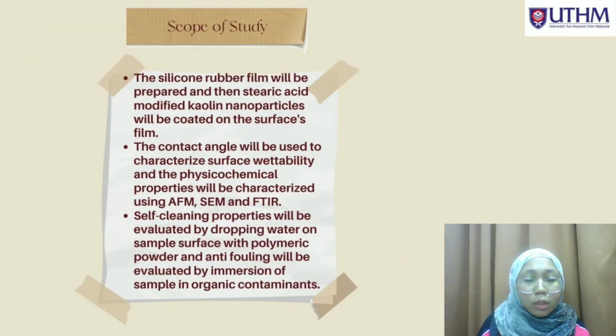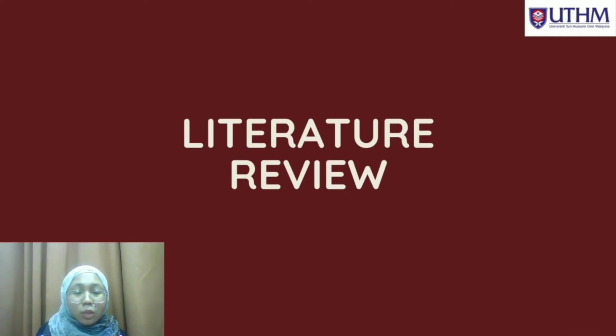Okay, to achieve the objectives, there are a few scopes of work identified as follows. First, the silicone rubber film will be prepared and then stearic acid modified kaolin nanoparticles will be coated on the film surface. Next, the contact angle will be used to characterize surface wettability and the physical-chemical properties will be characterized using AFM, SEM, and FTIR. The last one is the self-cleaning properties will be evaluated by dropping water on the sample surface covered with polymeric powder, and anti-fouling properties will be evaluated by immersion of the sample in organic contaminants.